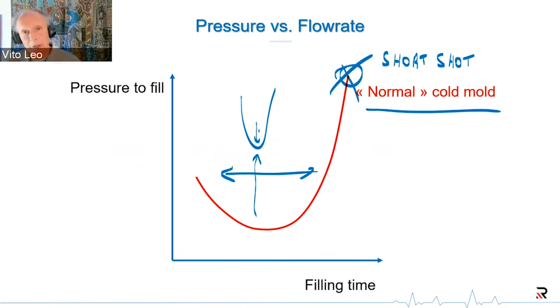And it's so typical for very small critical medical parts that people have found that, for instance, they can optimize this in a single cavity cold runner system, but when they move to a multi-cavity hot runner system, they have a problem because of the compressibility in the hot runner. They cannot match the required filling time. So the problem there is your processing window is far too narrow, and it makes your life extremely difficult.